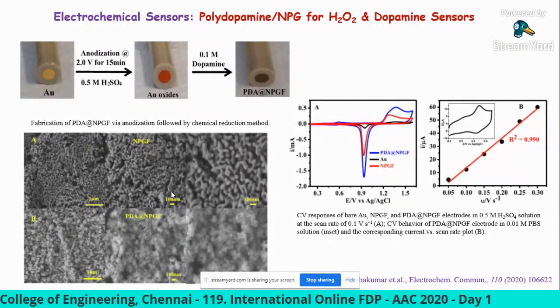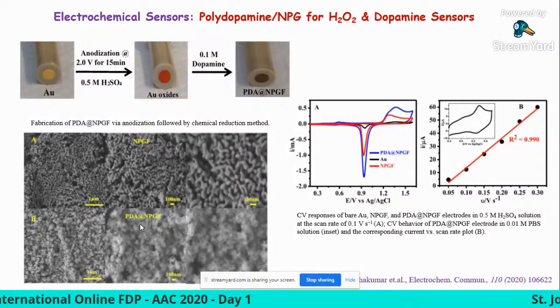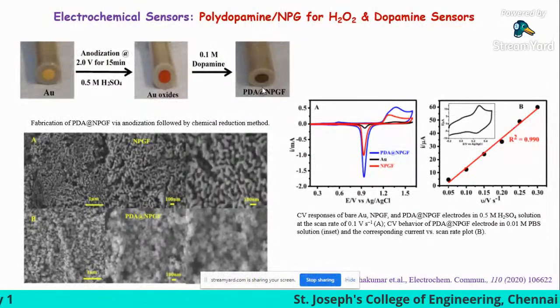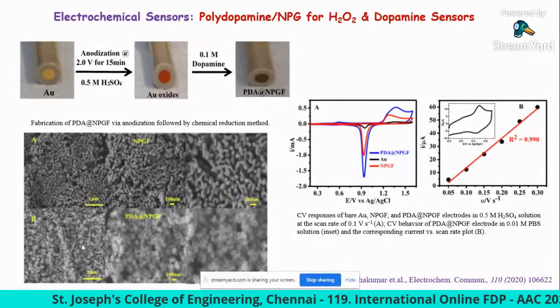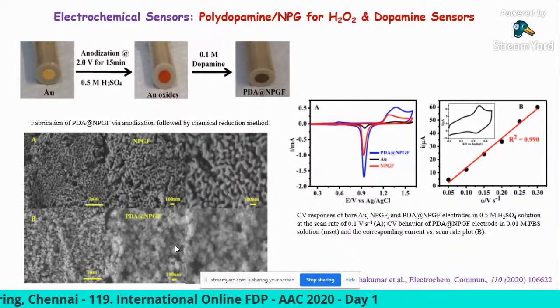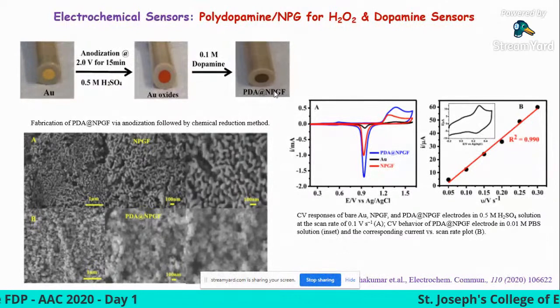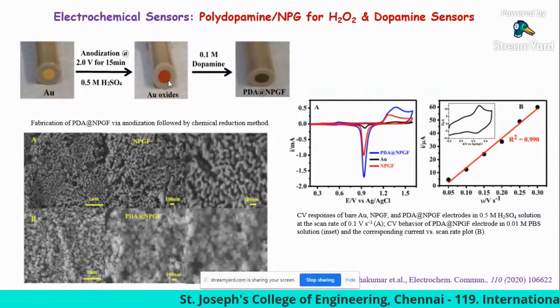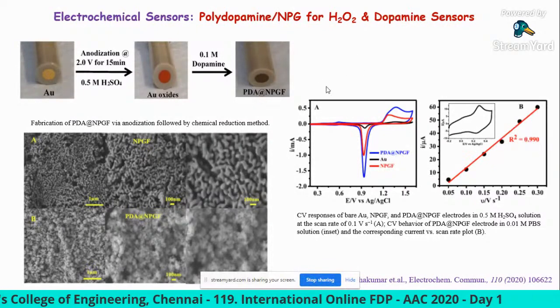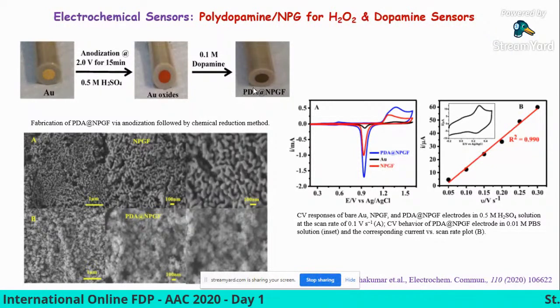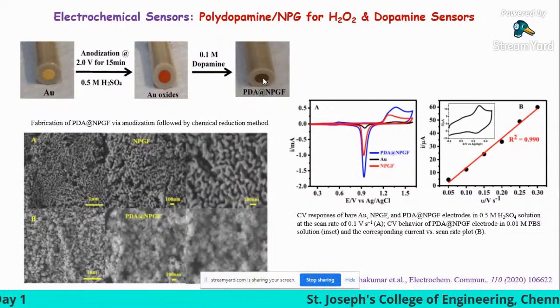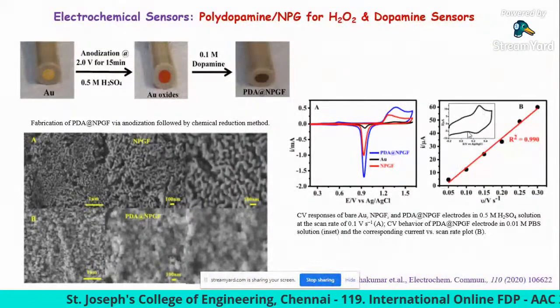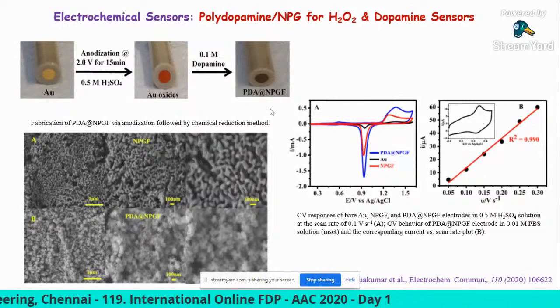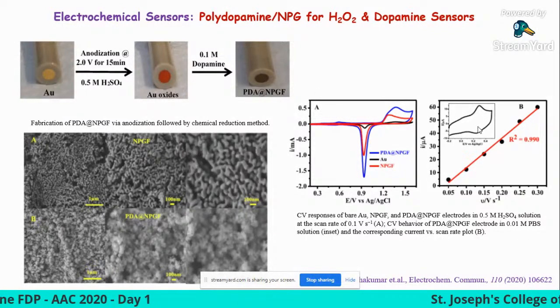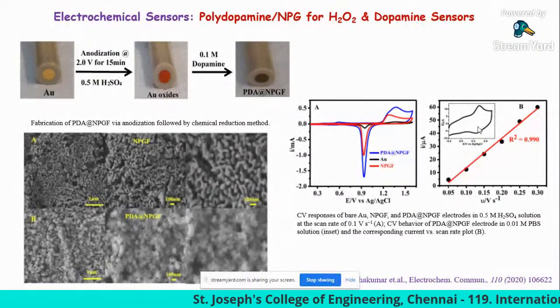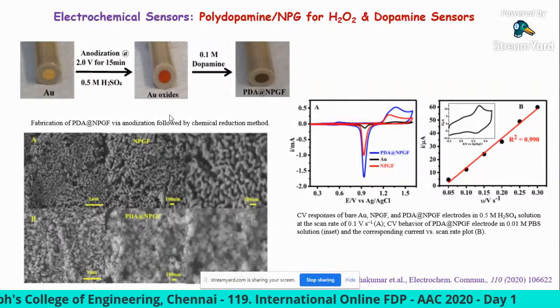So these are the corresponding scanning electron microscopic images of the nanoporous gold and polydopamine functionalized nanoporous gold. Initially we did not know whether polydopamine is present on the nanoporous gold. After taking the SEM images, we understood that polydopamine is present on the surface, because Au oxide is highly reactive and will oxidize the dopamine into polydopamine. Polydopamine has good adhesion behavior, so it adheres to the electrode surface, which is confirmed by cyclic voltammetric responses. This is the cyclic voltammetric response of polydopamine recorded in phosphate buffer solution without any dopamine analyte. This clearly confirmed the polydopamine was present on the electrode surface.